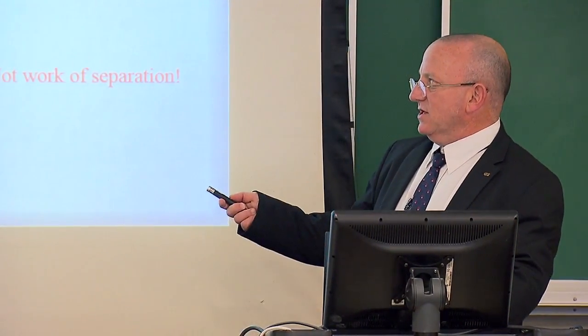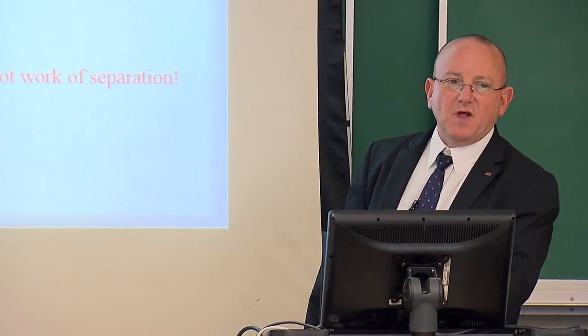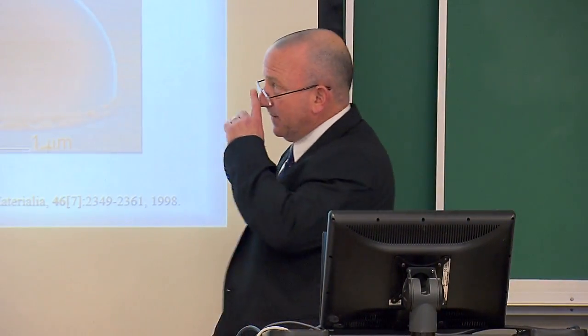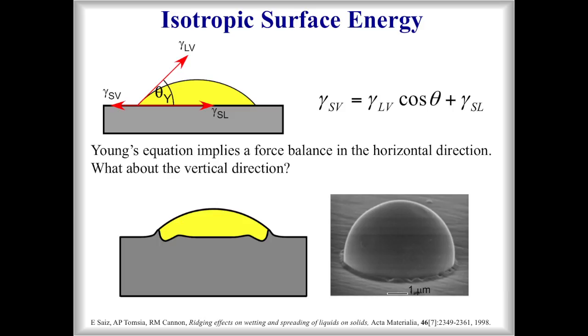Actually, the limitation is that it's correct as long as the interface is flat and coplanar with that of the surface. Why do I say that? Because if we were to really reach equilibrium, at least at the triple lines, what you would get here is a small ridge, and adjacent to it, a small trough.